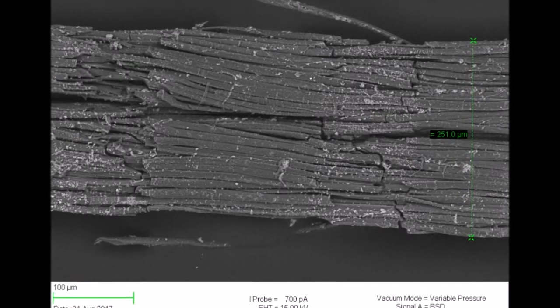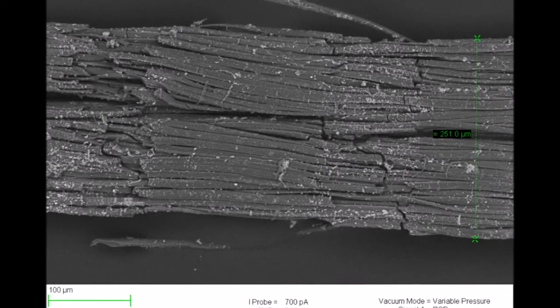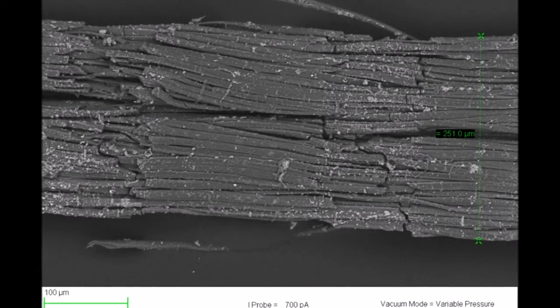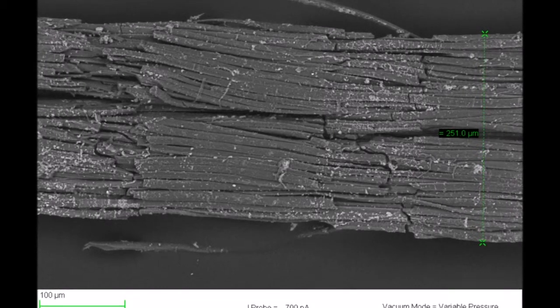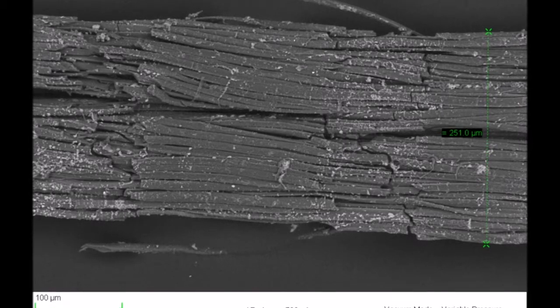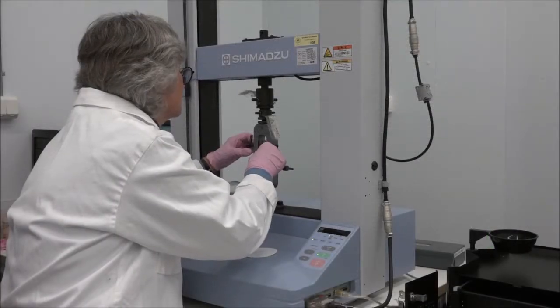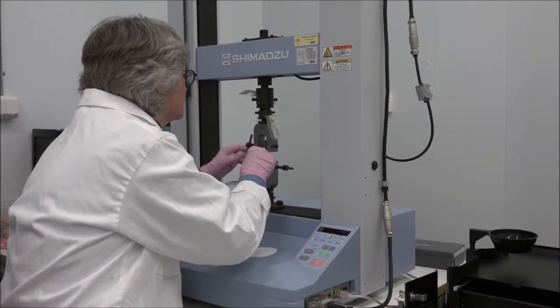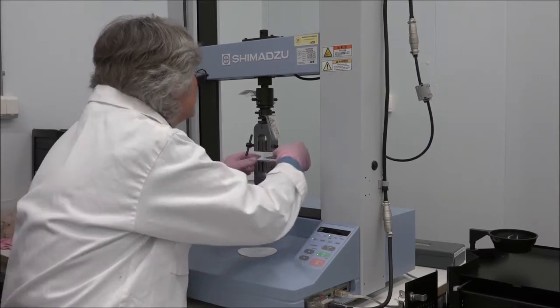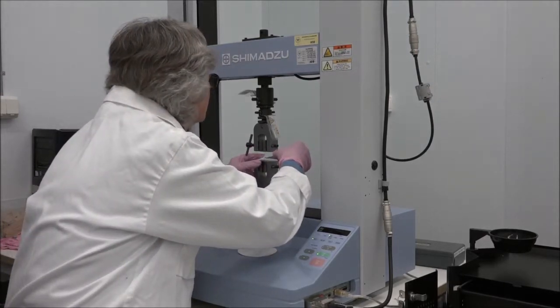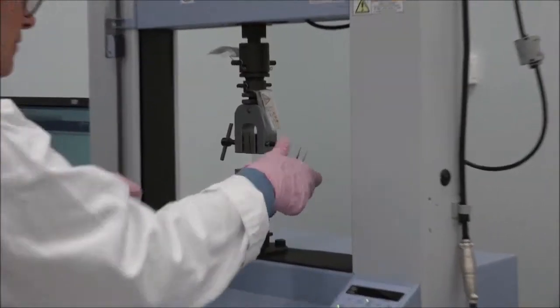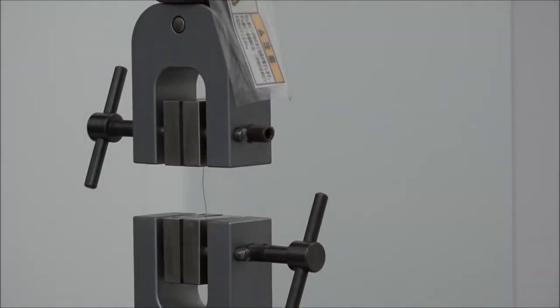The small dirt particles on the thread were found to contain aluminium, calcium, silicon and sulphur, probably pollutants from when the banner was exhibited in the Ridderholmen Church for many years. Tests carried out to investigate the tensile strength of the silk showed the fragile threads only retain a small amount of their original strength, in spite of their relatively good appearance. The results also indicate that the blue threads are maybe a little better preserved than the yellow.